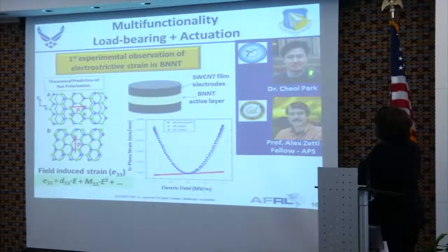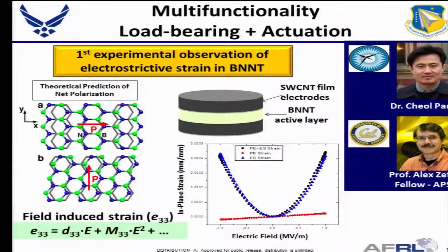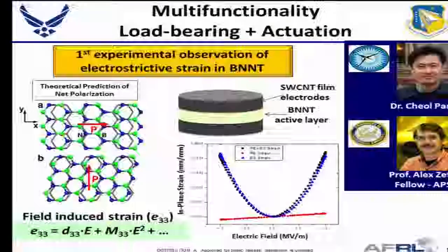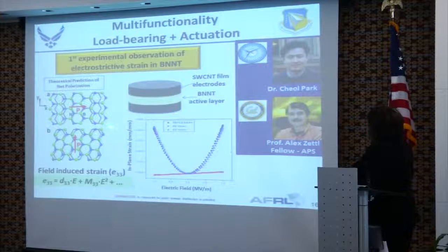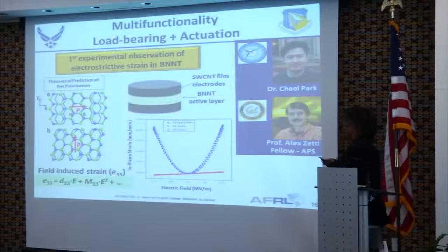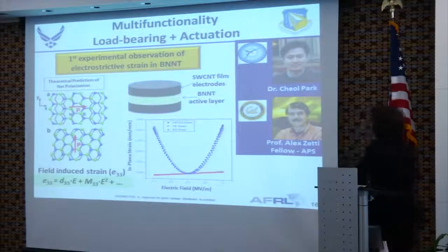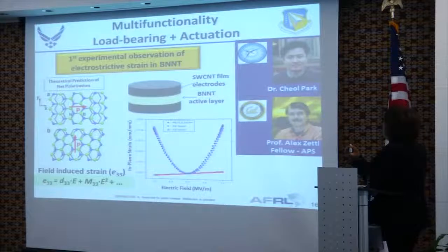Also, Dr. Park and Dr. Alex Zettl from Berkeley that I mentioned earlier are working together on this team, and they're looking at doing some of the first piezoelectric and electrostrictive measurements in these materials. I mentioned before that these have a net polarizability, so if you strain these, you see the polarization along the tube or normal to the tube, depending on if you strain it in torsion or tension or compression. And Dr.